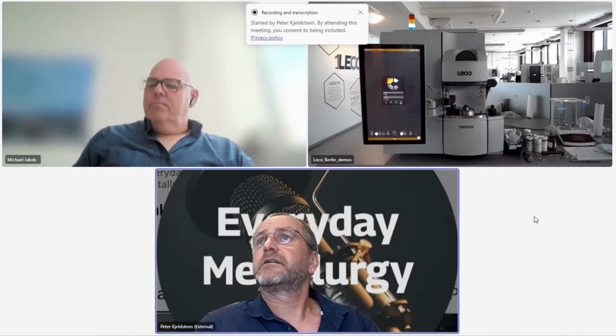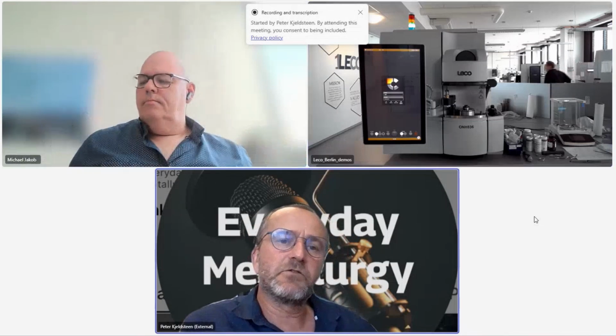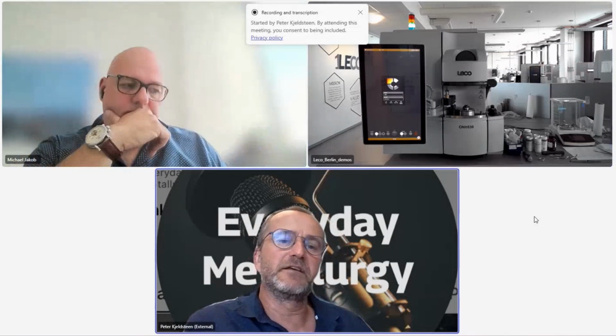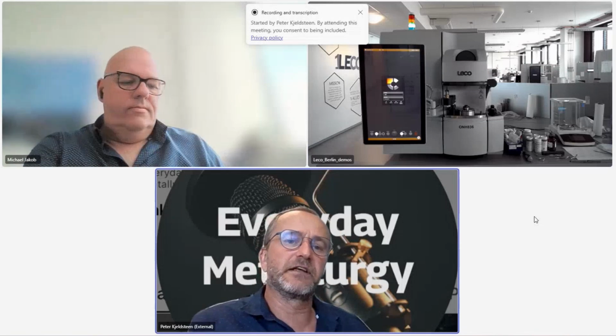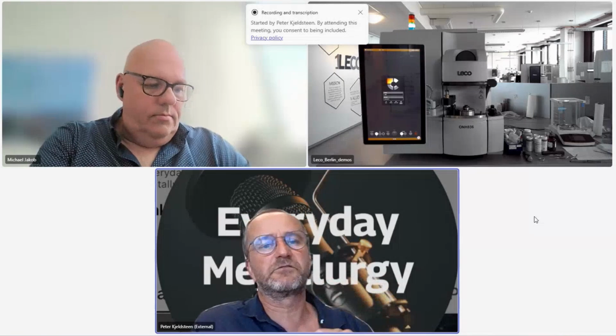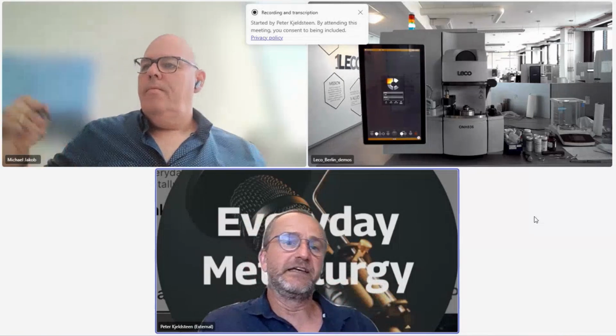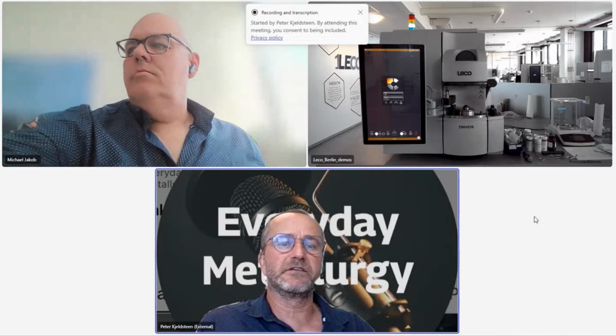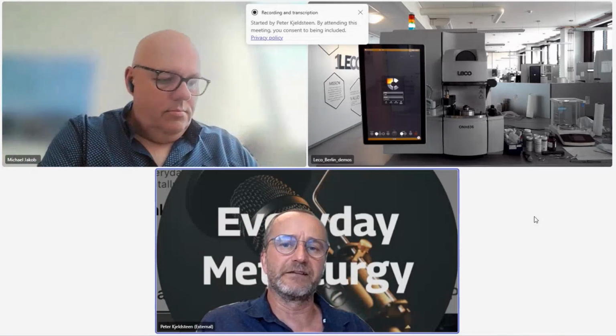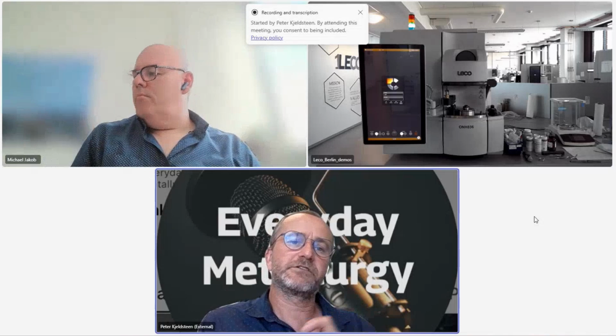We are making stainless steel, and we are now also making duplex stainless steel. That means that we are introducing nitrogen in the material, and the nitrogen has to be quite accurate to have the duplex structure, because nitrogen is an austenitic stabilizer about 30 times stronger than nickel. So therefore, accuracy of hitting the right amount of nitrogen is quite important.